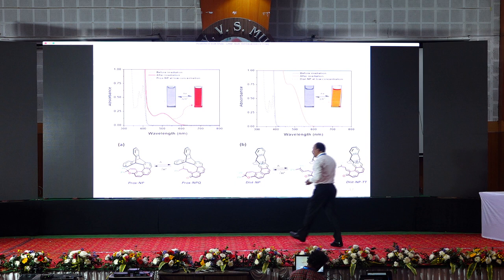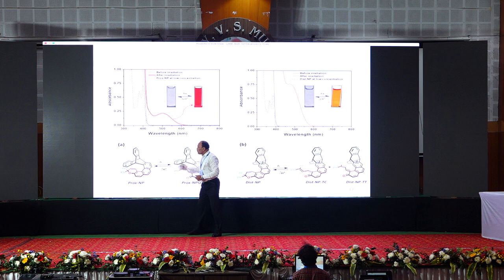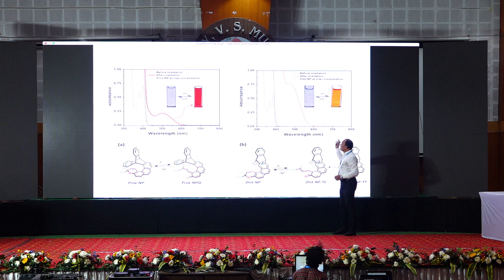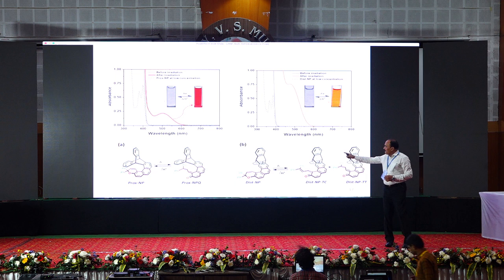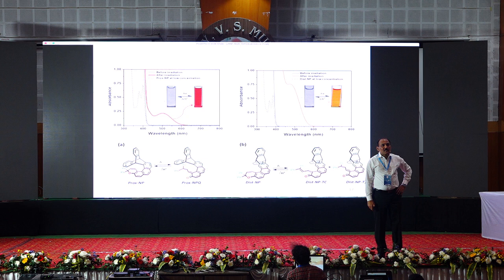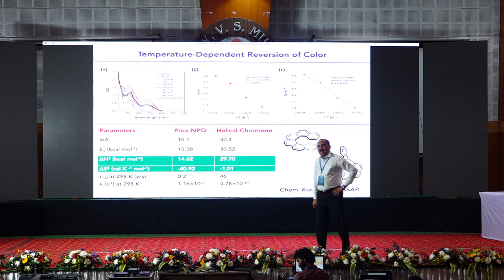The opened up form is much more relaxed than the constrained ring and would not like to go back. Whereas when the scaffold is really far away, there is no such issue. It basically goes and comes back within 2 minutes. In that particular case, it doesn't go back because the opened up form is really, really more relaxed. In other words, entropically, the product is more stable. In fact, it's one of the rare examples of entropically driven photochromism.